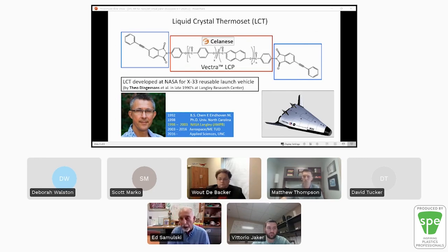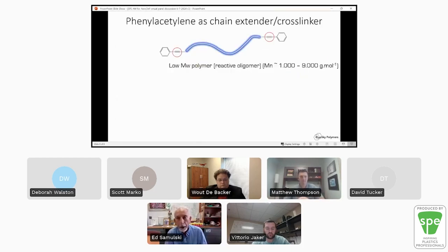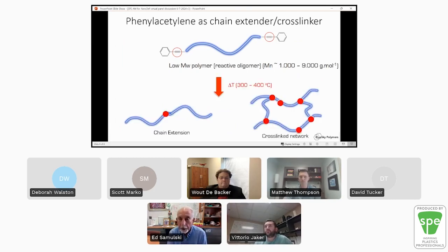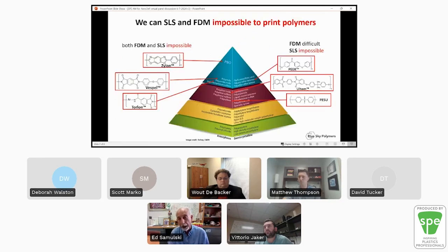Let's see what's on the next slide, Matthew. Sure. Yeah, so we said, why can't we do this with anything? We simply make an oligomer, terminate it with these reactive end groups, and those end groups are thermally activated. When you heat that up, you can either chain extend, depending on the temperature, and get to a high molecular weight polymer, or you can get to a 3D cross-linked network. And by working with an oligomer, before you do chain extension, you have a very low viscosity. So you can do things that you can't do with high molecular weight polymers. And this is when we realized that, gee, we can take this idea and move to the left side of the polymer pyramid and start making some of these very high performance polymers accessible.